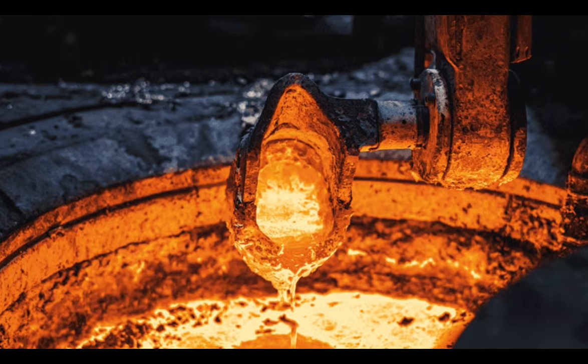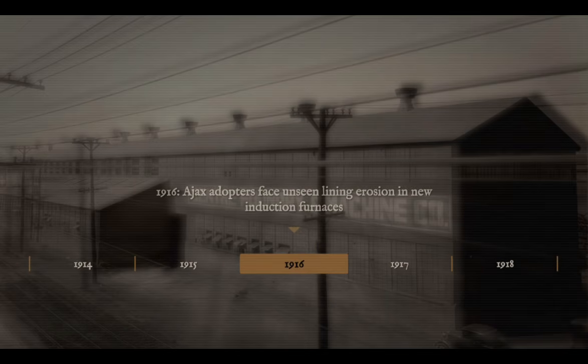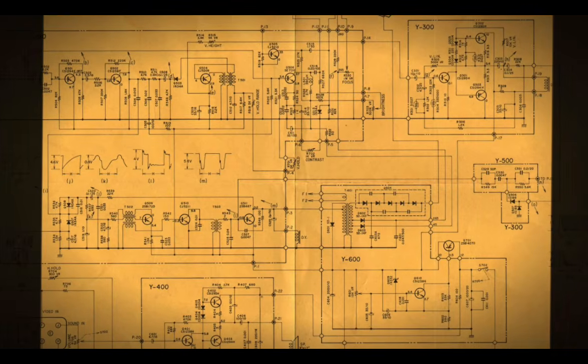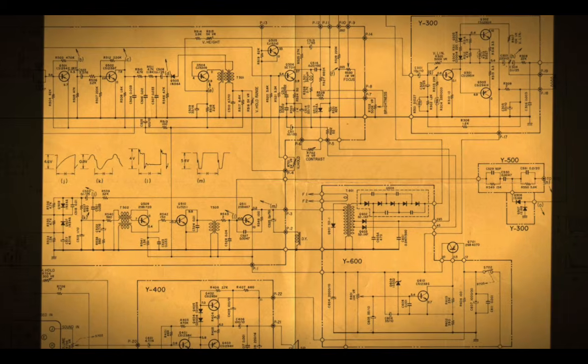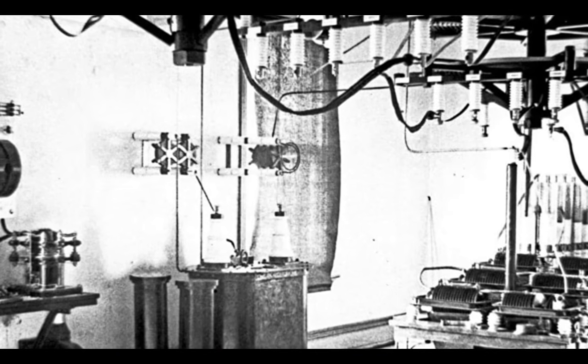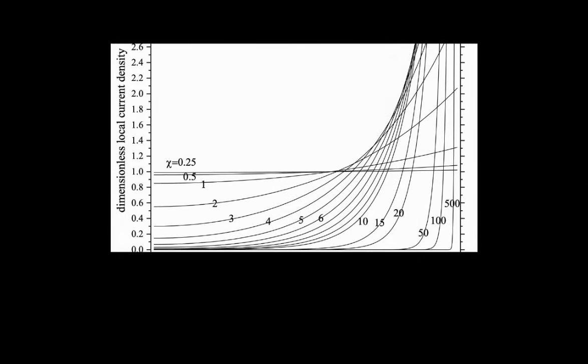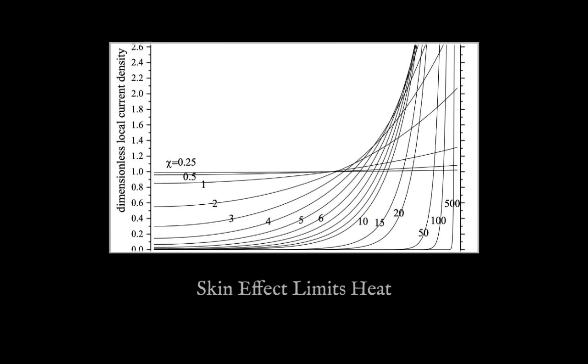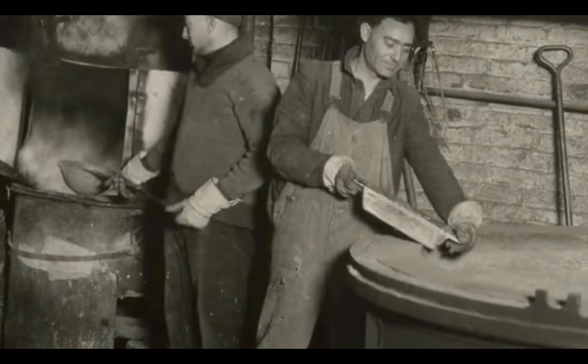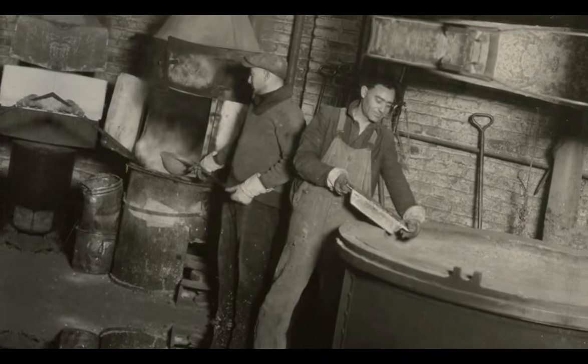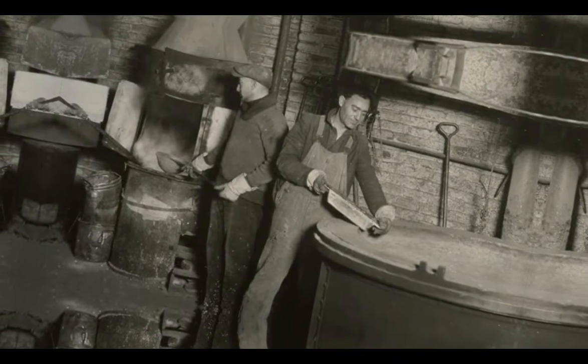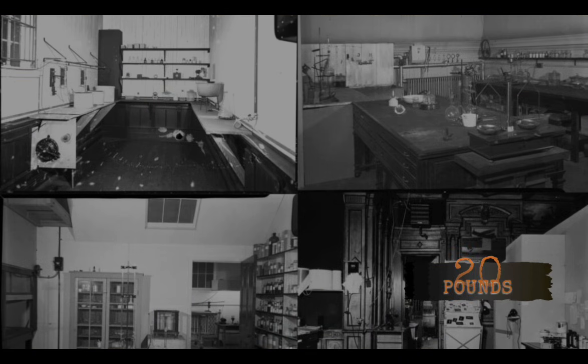inaccessible during operation. But the early adoption period, 1916 to the mid-1920s, introduced a second problem that the lining visibility issue compounded. Northrup's original patent operated at frequencies between 20,000 and 80,000 cycles per second, generated by spark gap oscillators. At those frequencies, the skin effect, the tendency of high-frequency alternating current to concentrate near the surface of a conductor, limited effective heating to thin charges. The spark gap furnaces of the earliest commercial period were useful for laboratory work and small-scale specialty heats, but 20 pounds of metal was the practical ceiling.